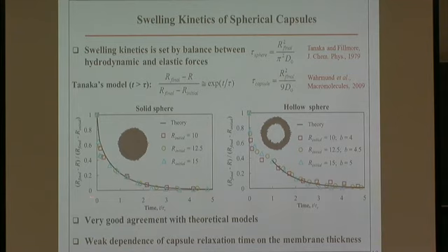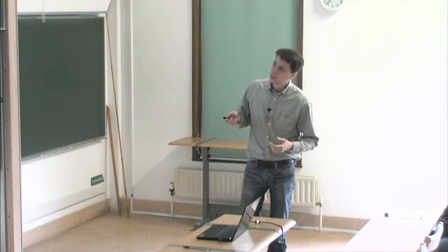So essentially this kinetics, as I told you, is defined by the balance between elastic forces, which is essentially the modulus of the network, and the drag force on the filament, and this is given by this parameter D, which is the ratio of these two, the collective diffusion. This is the parameter that essentially characterizes the network, the gel, and this is the characteristic time that tells how fast the gel will change.